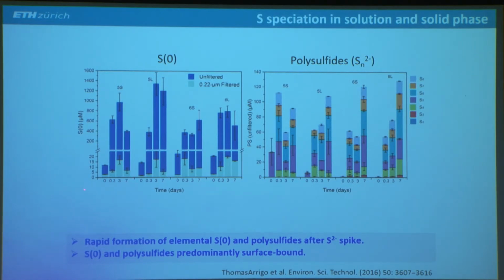And you can see that for all 4 different flocks, we have a very rapid increase in elemental sulfur. What you can also see is this is for unfiltered and for filtered samples. Unfiltered means this is the entire suspension. So it means basically the dark blue bars are elemental sulfur associated with solid phases, and the light blue bars are dissolved elemental sulfur. So it means that most of the elemental sulfur formed was associated with the particles.